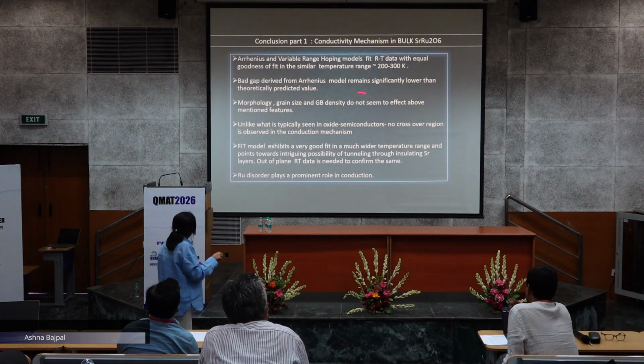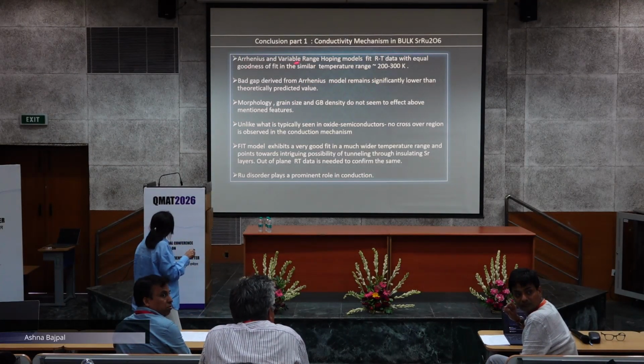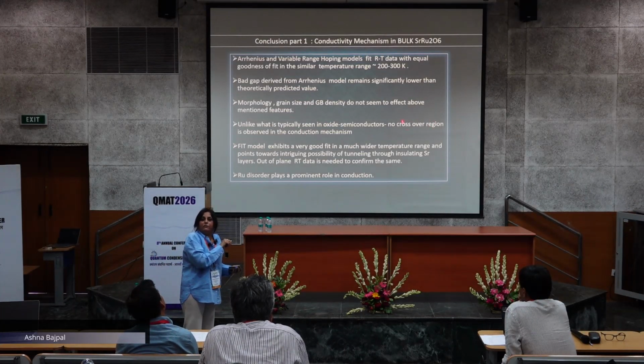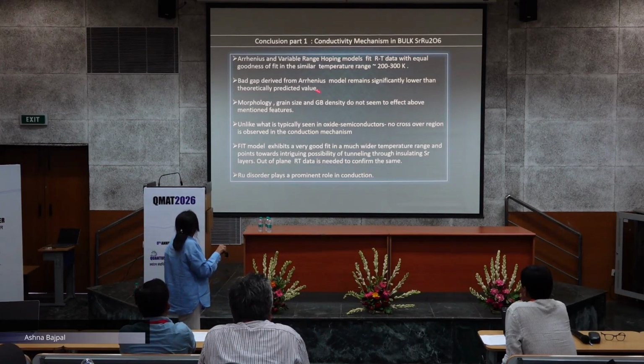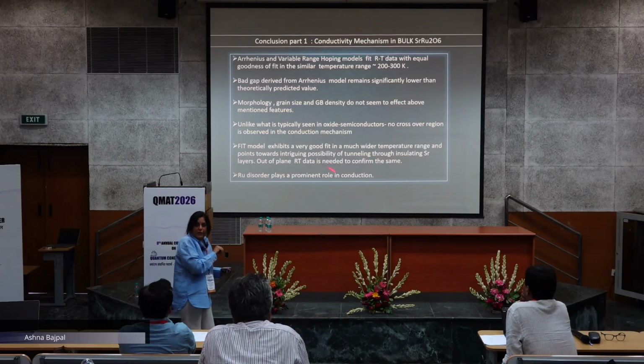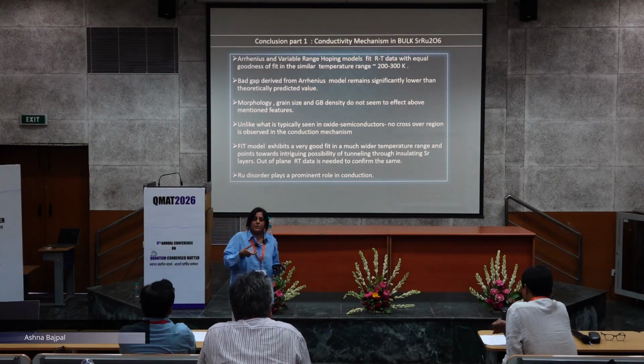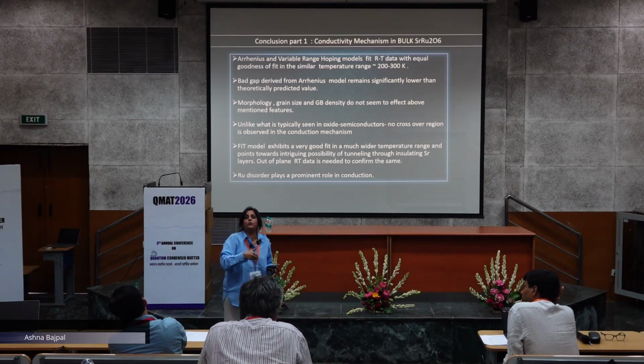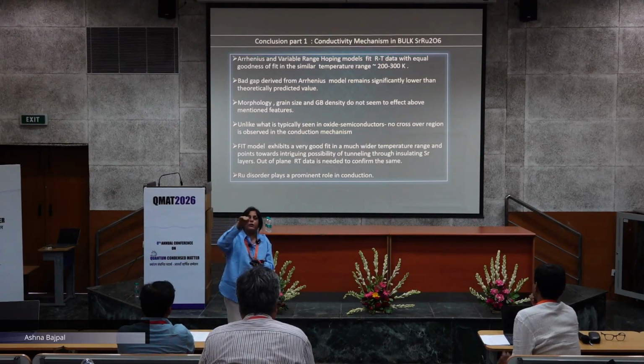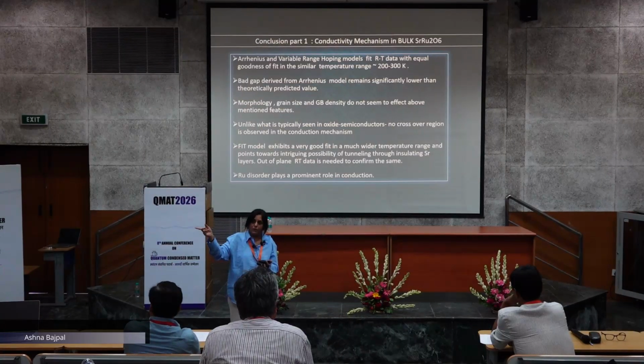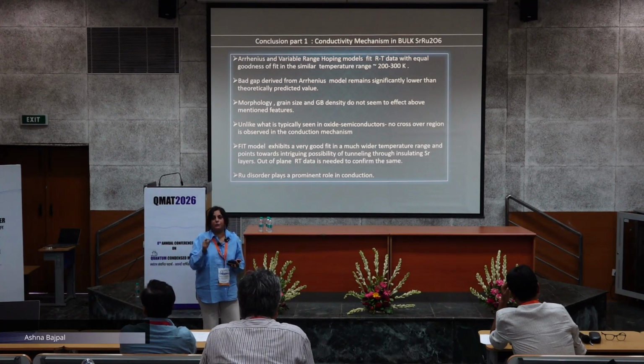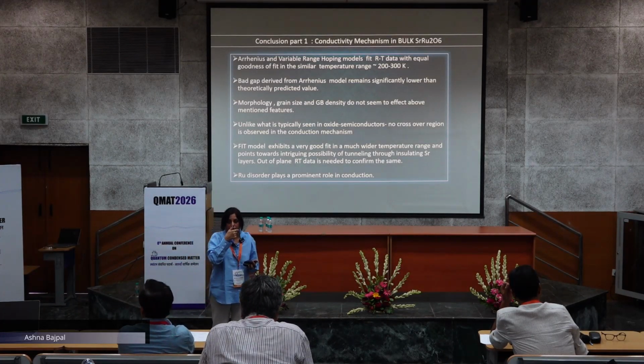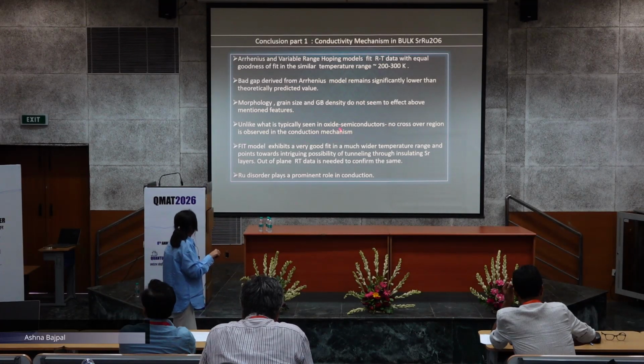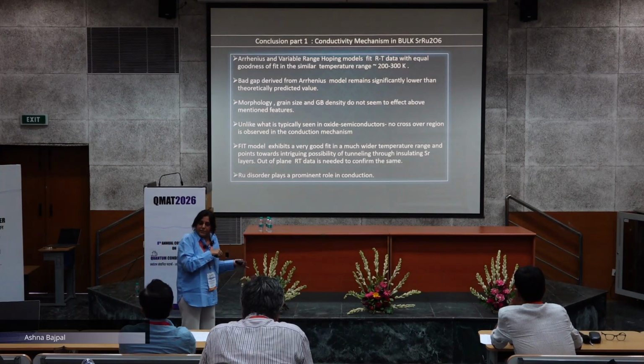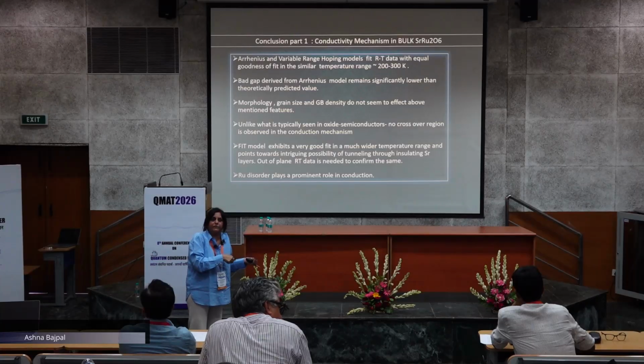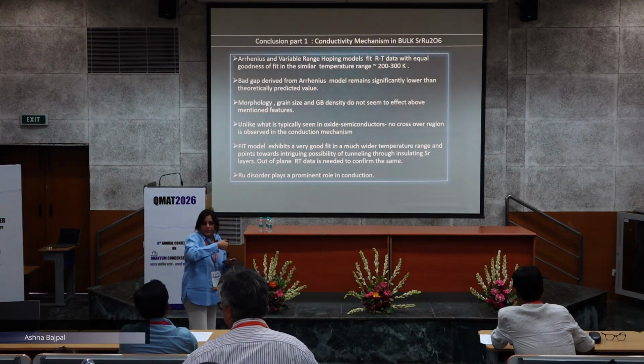So that is the conclusion of the first part. We found that Arrhenius and variable range hopping, all the variants of variable range hopping, fit equally well in a similar temperature range. The band gap derived from the Arrhenius model remains significantly lower than the theoretically predicted value, and now we realize that this is a system where multiple conduction mechanisms are likely to coexist. You may have transitions from valence band to conduction band. You may have a lot of defect levels near the Fermi level which perhaps enable hopping, but the most prominent mechanism from our analysis seems to be fluctuation induced tunneling conductance, and this gives us the possibility that this could be a very interesting sample from its electronic point of view. It could be very interesting if we have this measurement on a single crystallite.